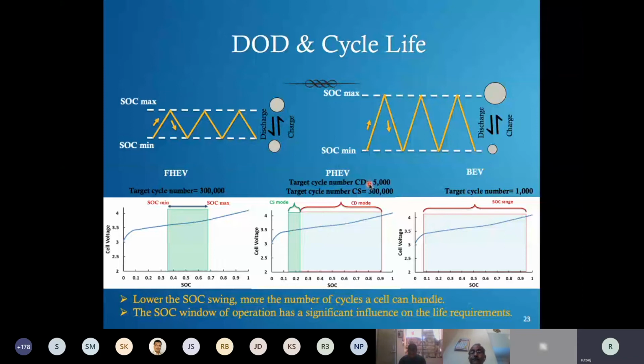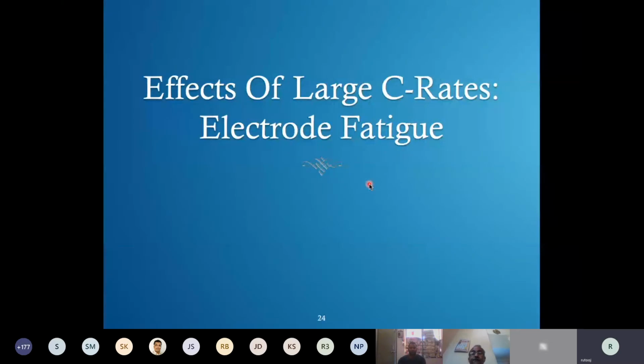Going to the second effect of cycling, typically you would see this second effect when you have large C rates of operation. So you are charging and discharging at relatively larger C rates. Again, large is a very subjective term. For example, for a power cell, even 2C, 3C may not be large C rates. For an energy cell, even 0.5C or 1C could be a large C rate. So it's a cell design specific term, but we will have to look at the C rate for that particular design.